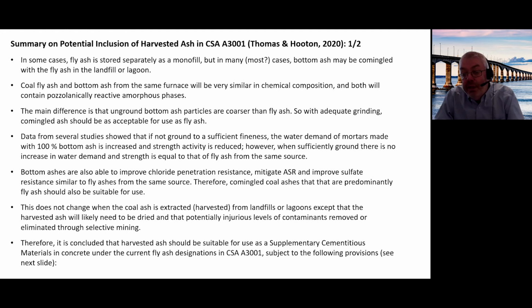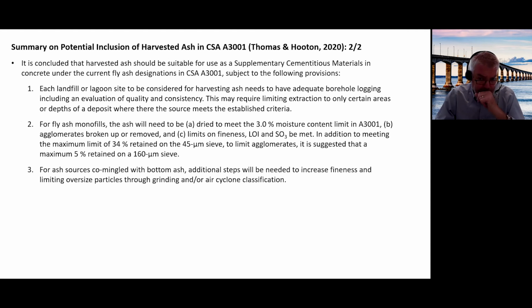So therefore, commingled coal ashes that contain fly ash and bottom ash, once ground, should be entirely suitable for use in concrete. We have a few caveats on this in our Canadian standards. And obviously, the landfill and lagoon sites have to be adequately logged and evaluated prior to use, and ensure that any deleterious materials are identified and removed.